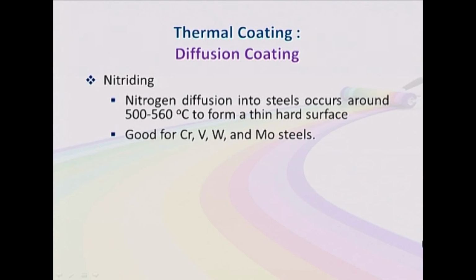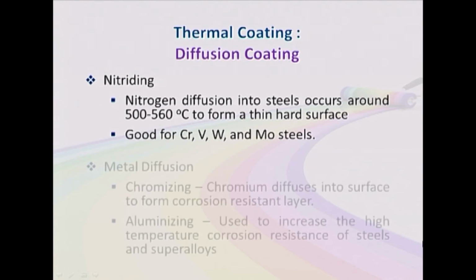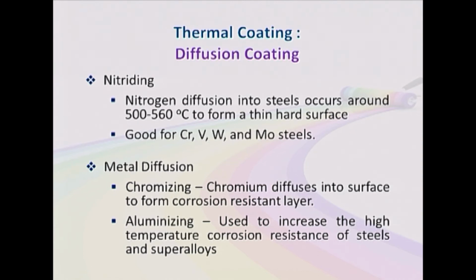In the nitriding method, nitrogen is diffused into steel and it occurs around a temperature range from 500 to 560 degrees Celsius, and a very hard thin surface is formed. This type of coating is good for chromium, vanadium, tungsten and molybdenum steels. Next is metal diffusion. Here metals such as chromium or aluminium are diffused into the surface to form a corrosion resistant layer. In case of aluminium, it is used to increase the high temperature corrosion resistance of steels and superalloys.